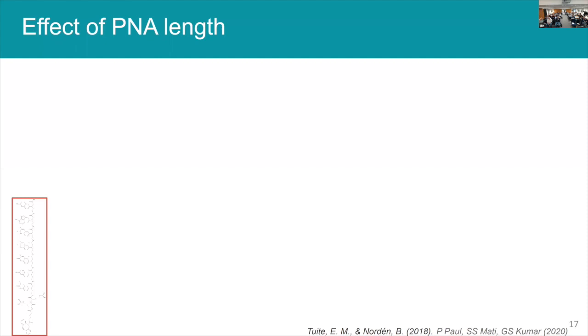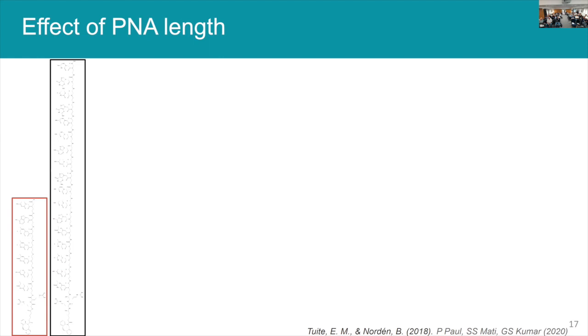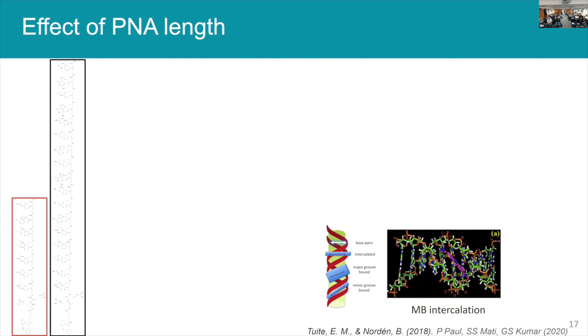By this time, we had optimized our solid phase peptide synthesis to be able to do longer PNA synthesis. Great. So we went up to a 17-mer PNA. It's exactly the same thing as I said, same functional group, but we have a much longer peptide nucleic acid. And so ideally, this means that, based on the literature, methylene blue can interact, as I said, in many different ways. Spectroscopic analysis says that it's most commonly this intercalation effect.